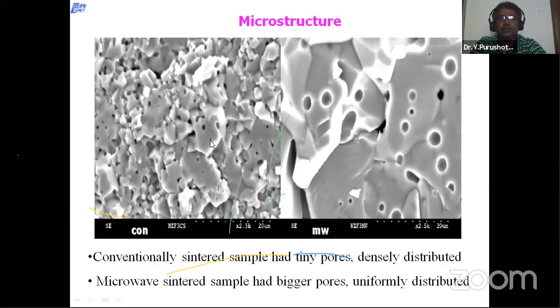And if you see the microstructure, the conventionally sintered samples had tiny pores densely distributed, whereas the microwave sintered had bigger pores, uniformly distributed. That is what we observed.